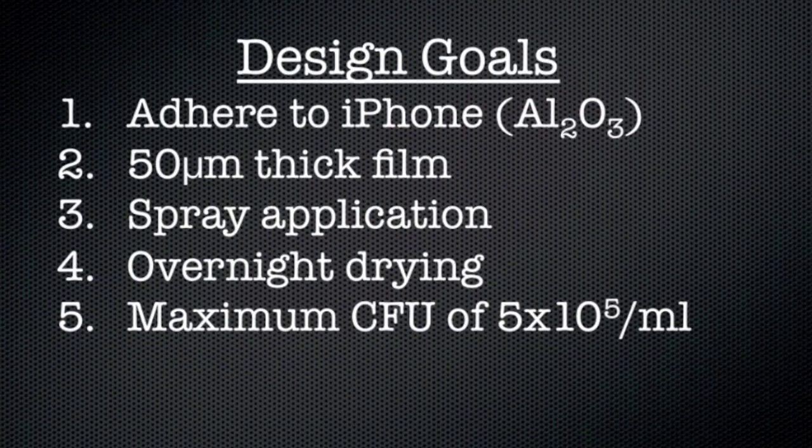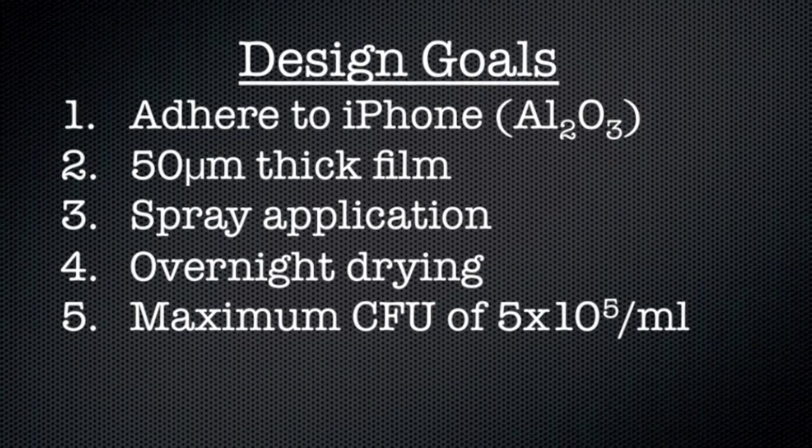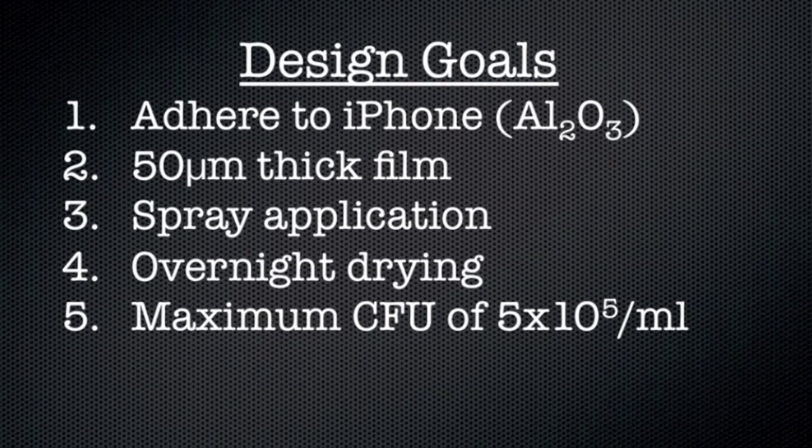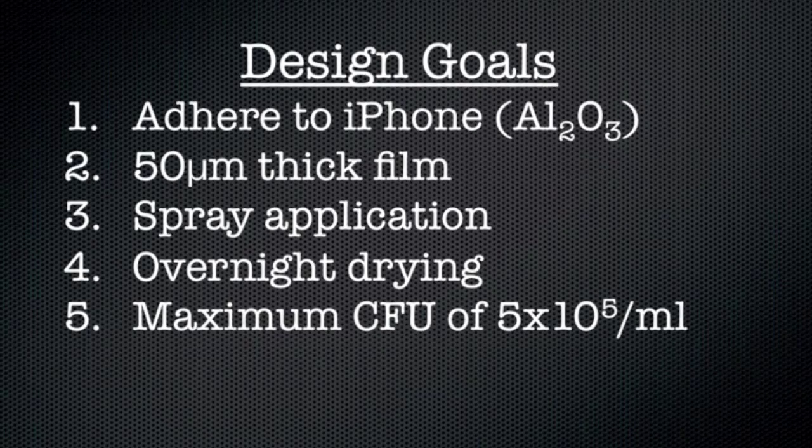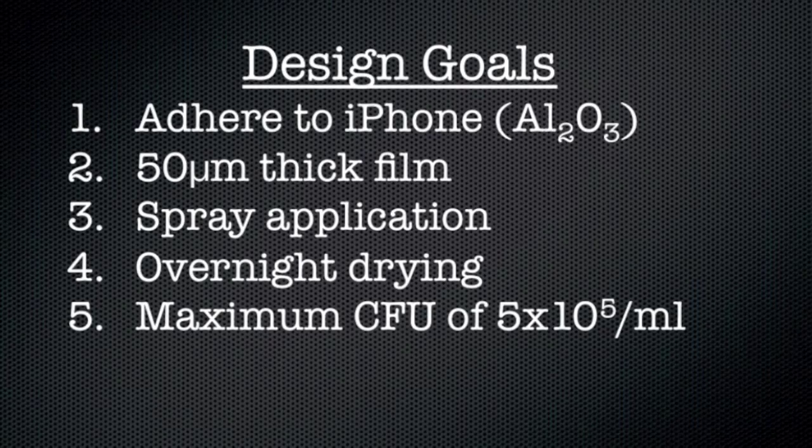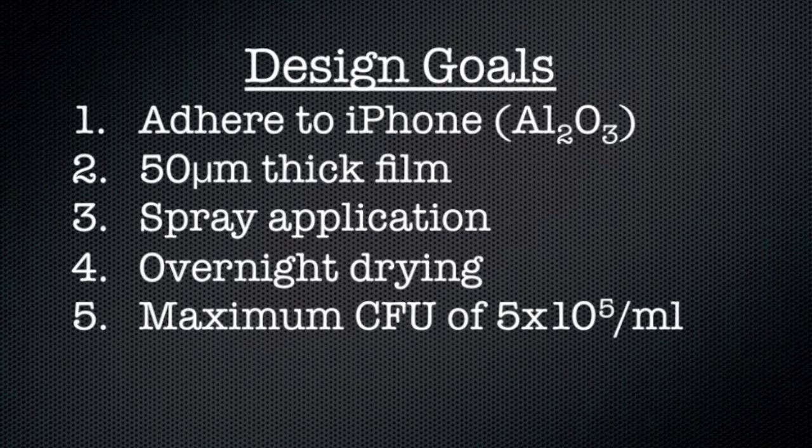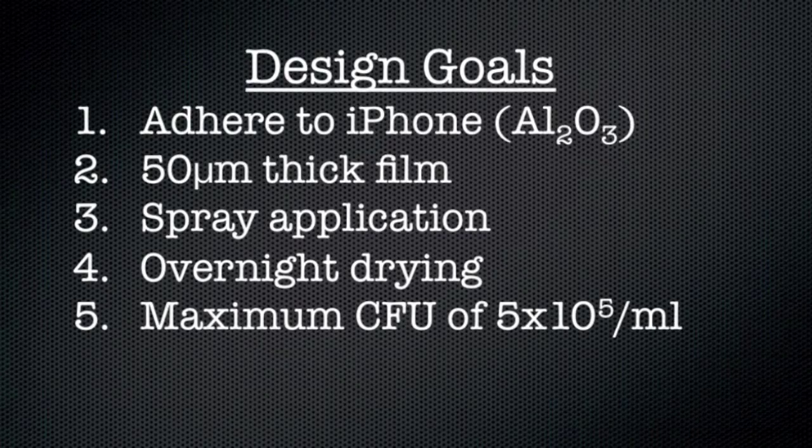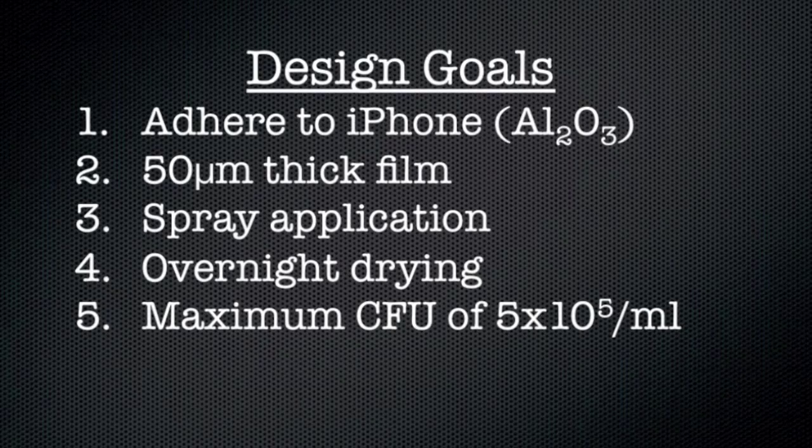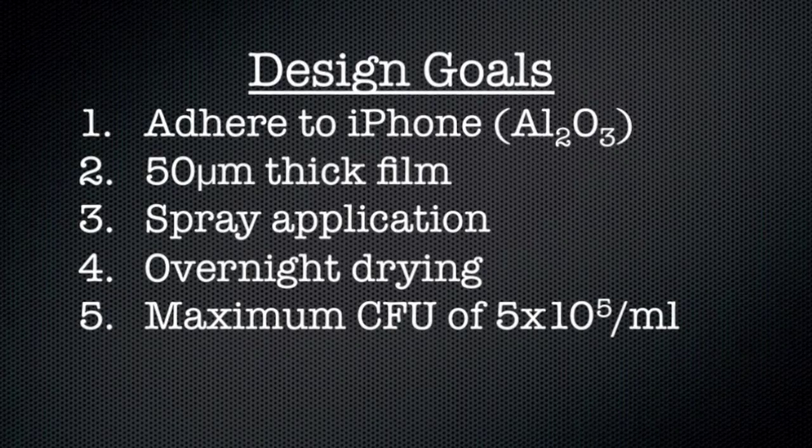Now I want to go over the design goals for our film. We wanted to adhere to the backside of the iPhone which is an aluminum oxide surface, be no more than 50 microns thick which is comparable to protective screens or other films used for phones, have a spray application method that would dry overnight into a film, and have a maximum colony forming unit of 5×10^5 per milliliter, which is a measure of the antibacterial efficacy of films or other antibacterial surfaces.